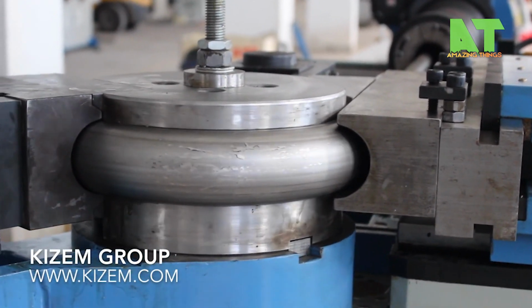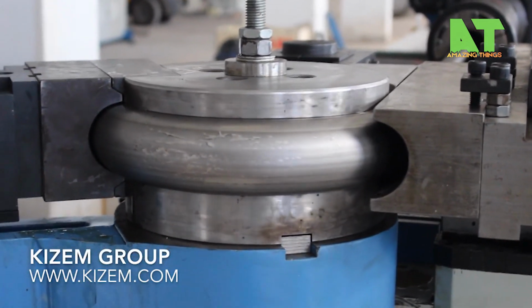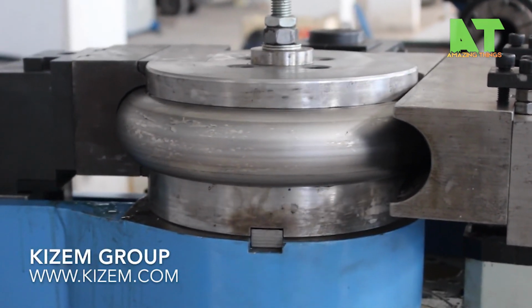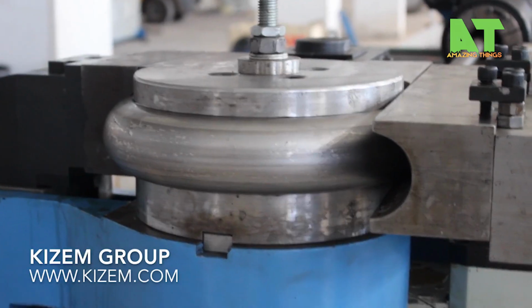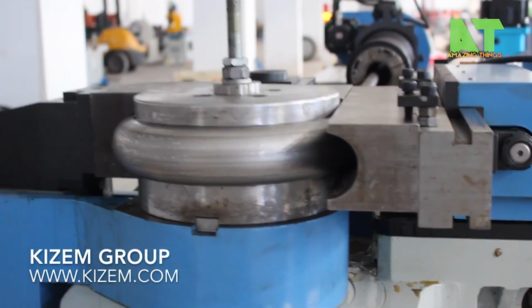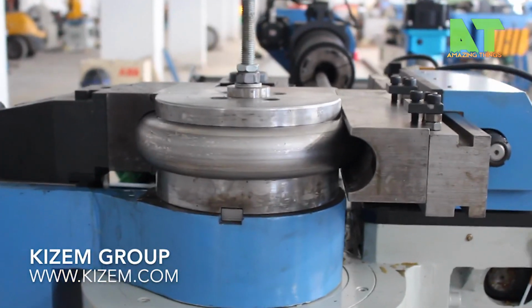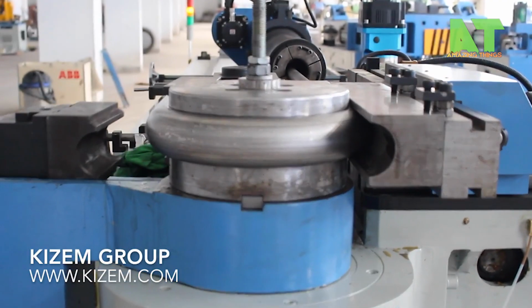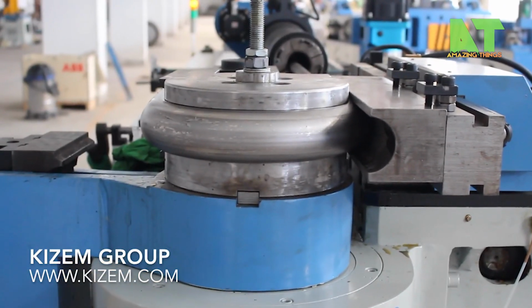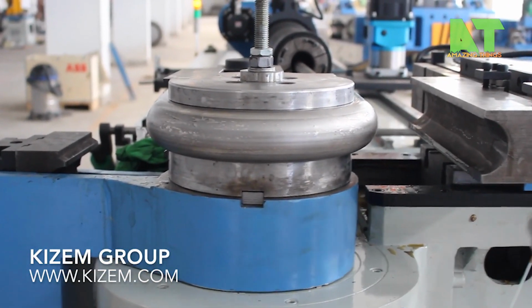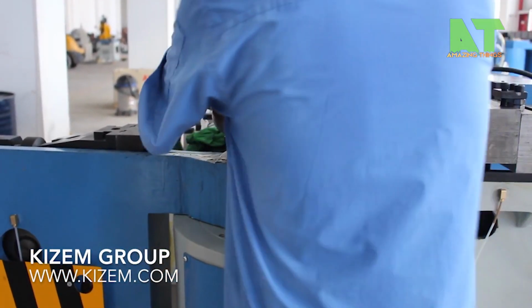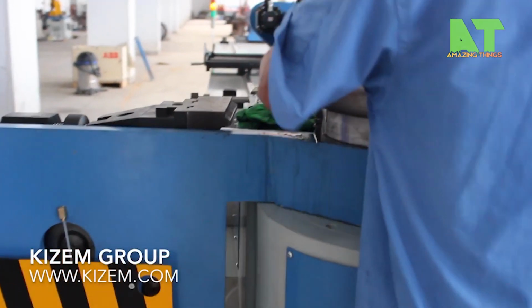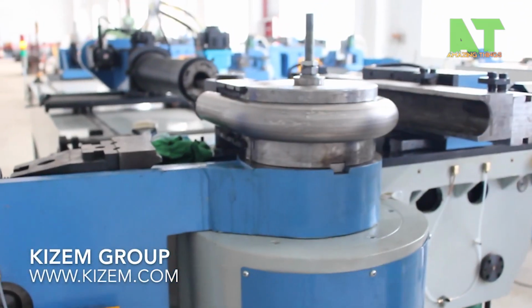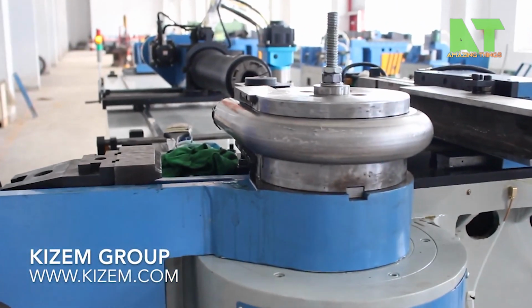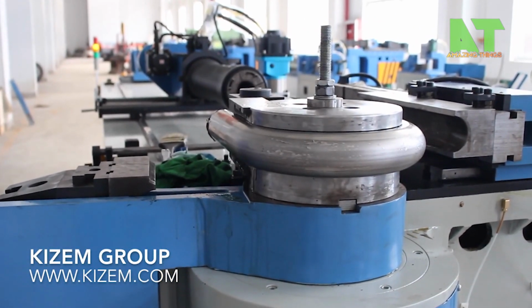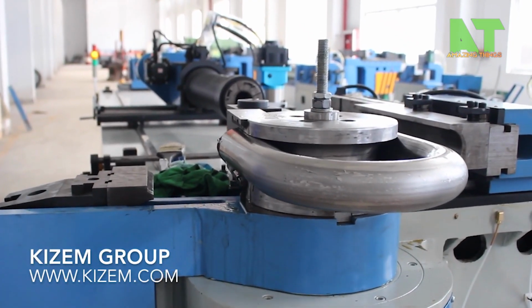The Kizem bender uses a mandrel bending process. As the tube is bent around a precision die, a mandrel, a shaped steel plug on a flexible rod, sits inside the tube at the exact point of the bend. It supports the tube wall from the inside, preventing collapse and wrinkling. A pressure die pushes from the outside. A wiper die prevents material from buckling at the inner radius. CNC control manages every parameter, bend angle, rotation, and feed, all programmed to fractions of a degree.